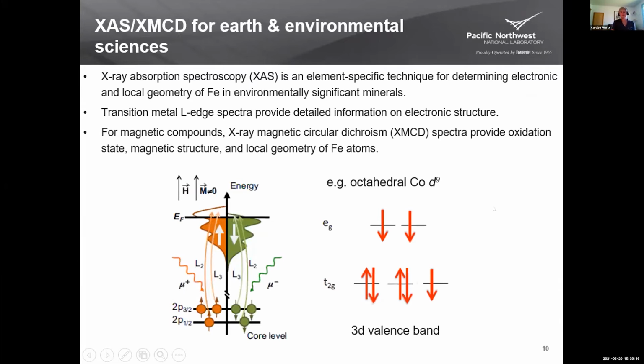The technique we use to look at the magnetite and characterize its interaction with the solution and contaminants that are presently in the solution is based on X-ray absorption spectroscopy, which is an elemental specific technique for determining electronic and local geometry of iron or any transition metals in environmentally significant minerals. So it's slightly different from K-edge spectroscopy in that it provides more information on the electronic structure. And certainly for magnetic compounds such as magnetite, it gives you the opportunity to determine not only the oxidation state of the iron, but also the local geometry of the iron and the oxidation state in that local geometry.